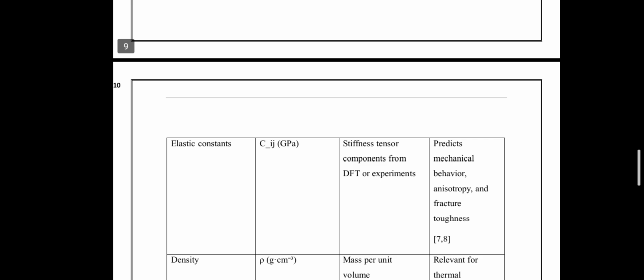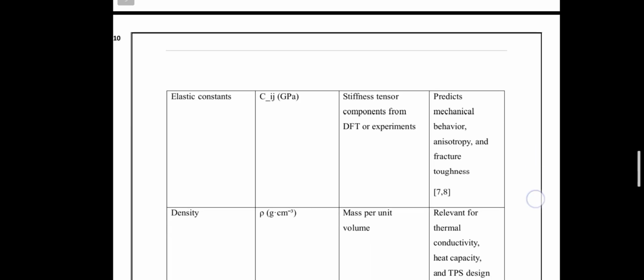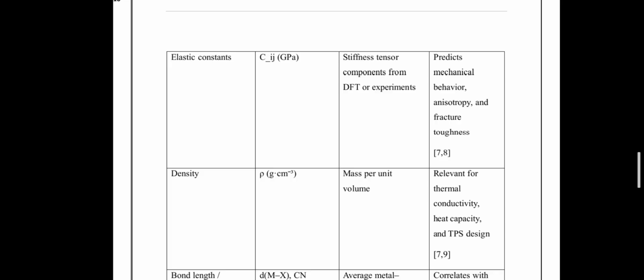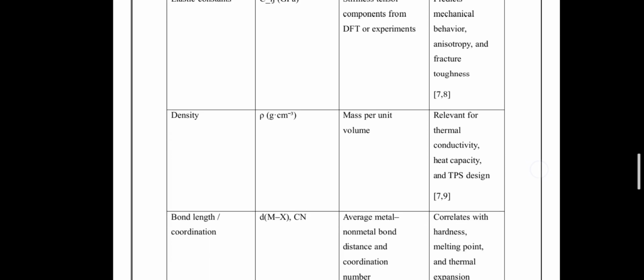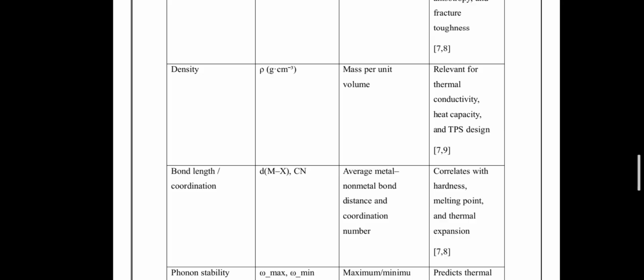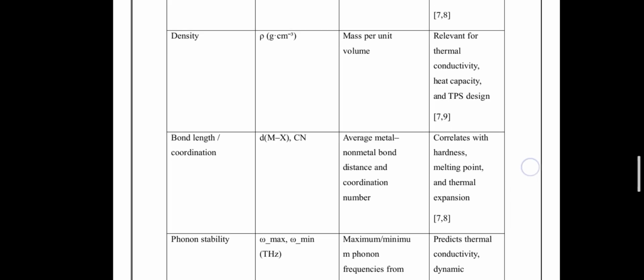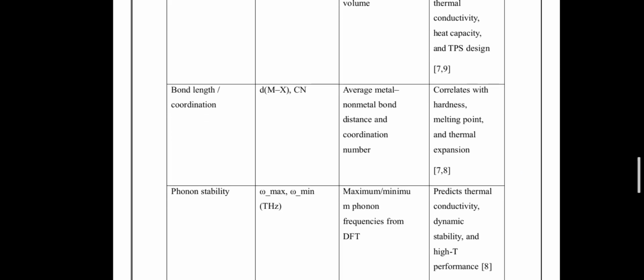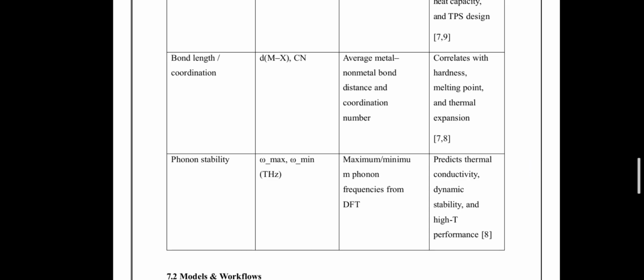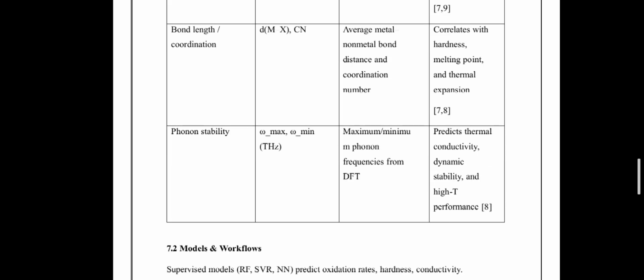Elastic constant tells about the stiffness components from DFT or experiment. It predicts the mechanical behavior, anisotropy, and fracture toughness. Density, mass per unit volume, is relevant for thermal conductivity, heat capacity, and TPS design. Bond length and coordination, the average metal non metal bond distance and the coordination number, correlate with the hardness, melting point, and thermal expansion of the ultra high temperature ceramics. Phonon stability, that is the maximum or minimum phonon frequency from DFT, predicts the thermal conductivity, dynamic stability, and high temperature performance. So these are some descriptors that we feed in our machine learning.